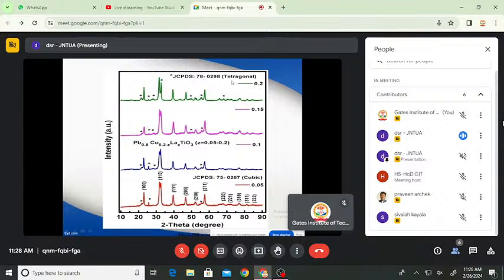Which means that as the lead cations were varied with the corresponding lanthanum cations, the PCLT nanoparticles exhibited tetragonal phases, and at the same time, cubic reflection planes were achieved. They achieved the required phases by altering the cobalt content with respect to the lanthanum content. This explains the fact that a change of small concentration of cobalt cations may dominate rather than the variation of lead cations. Also, fine crystallinity and broad width of diffraction peaks were observed. The fine crystallinity and broad width of the diffraction peaks explain the presence of nano-sized particles and crystallites.